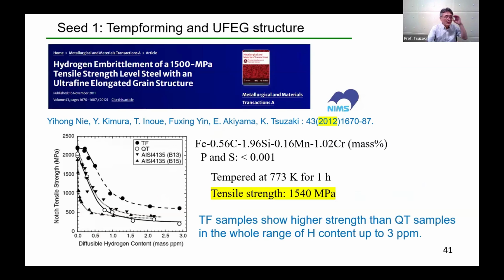We have ideas for overcoming hydrogen embrittlement. One is again temp-forming, an ultrafine elongated grain structure. In 2012, we reported that the TF sample shows higher strength than QT in the whole range of hydrogen content up to 3 ppm, as shown here in this figure. The result was obtained in this high carbon, low alloy steel with a very low level of phosphorus and sulfur.